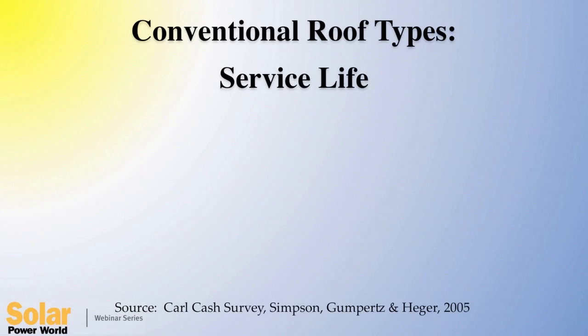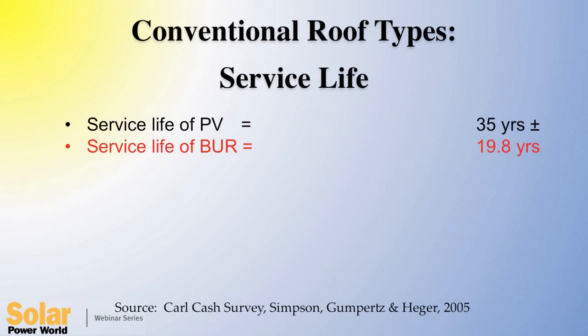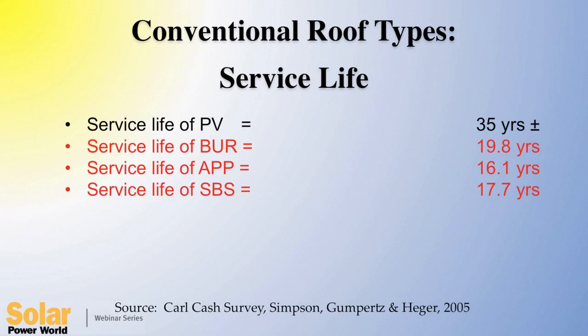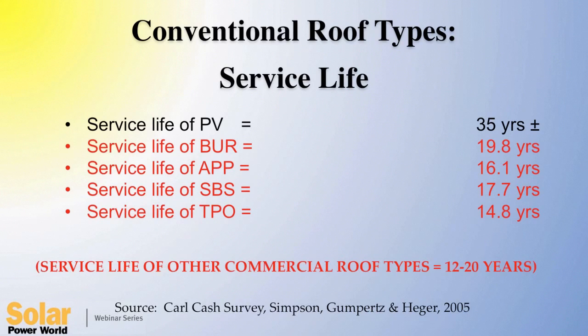So let's take a look at the service life of some conventional roof types. This survey, by the way, was put together by Carl Cash, who works for Simpson Gumpertz & Heger, a well-respected roof consulting firm with offices all over the U.S. And it was based on a nationwide survey that they did of the entire roofing industry. So here we see the service life of built-up roofing at 19.8 years, APP modified asphalt at 16, SBS modified asphalt at 17, and TPO at 14.8. Service life of other commercial roof types, not shown here but included in that survey, ranged between 12 and 20 years.